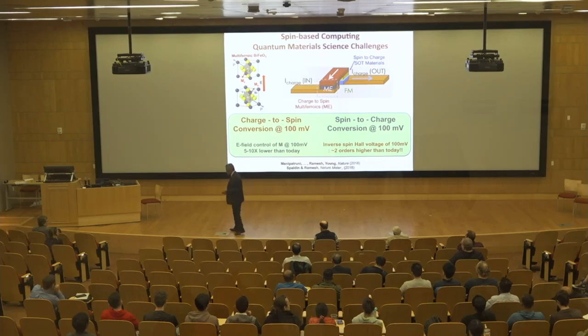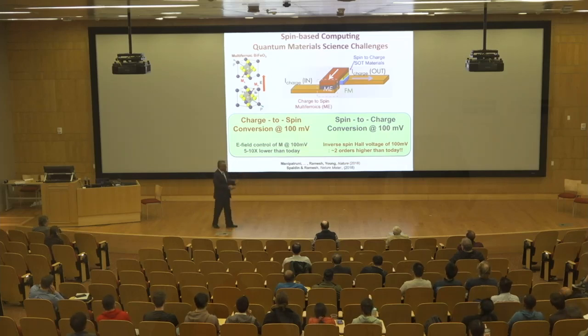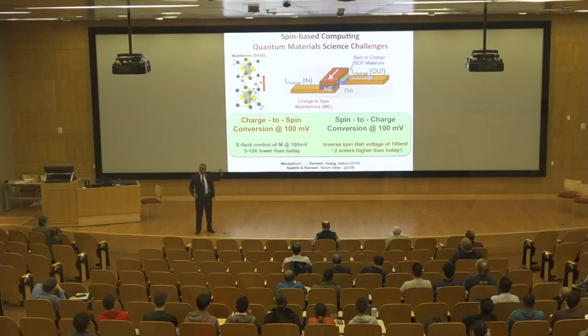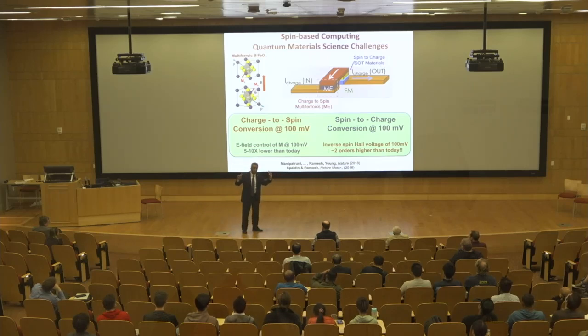What they wanted us to do was to take them through how this material would work. Nina worked on it for 2 years of her fellowship. This material is bismuth iron oxide, which is a very fascinating material. In terms of how this would work, you have a voltage input with a metal wire, for example, that would manipulate the magnetoelectric multiferroic material. You would switch the polarization. The coupling between the magnetism and the polarization, the spin and the charge degrees of freedom, then changes the magnetic state. Then you do all of your logic operations in spin space. You can do spin-based logic. Then you read it out with something called the inverse spin Hall effect. All of this is fine.